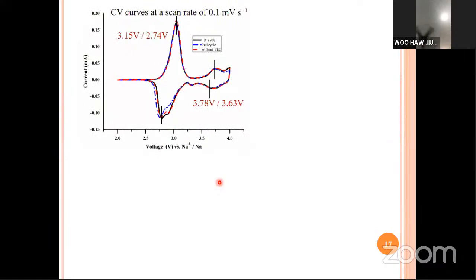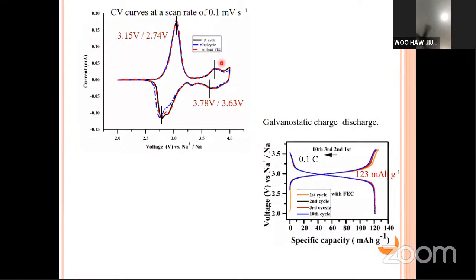This is the CV result. Now, there are basically two pairs of redox peaks. First, the 3.15 volt and 2.74 volt pair represents the high spin Fe2+ to Fe3+. And then the second pair at 3.78 volt and 3.63 volt represents the low spin Fe2+ to Fe3+. And then we also ran the GCD. This is what we obtained at 0.1 C rate. We are getting 123 milliampere hour per gram. This result is considered quite good.